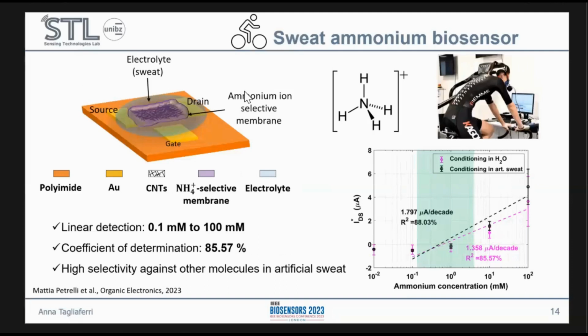This led to a slight improvement in the stability of the carbon nanotubes, and we found a linear detection range, which is much higher, but it still covers the whole physiological range of ammonium that is produced in sweat during activity. The coefficient of determination in this case was also not great, but further improvements have been made, and a new device is being developed right now. What is important to note here is that this type of biosensor was tested in artificial sweat, and it still got a very high selectivity against the other ions that are typically present in sweat.